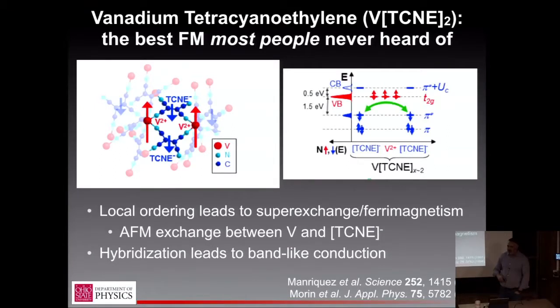I like to think of those as isolated. Well, let's say it's continuous. The issue is, and it's kind of hard to tell from this diagram, that not all of the TCNEs are connected to vanadium on all of their terminal groups. So that means some of them are free to rotate. So while, hypothetically, you can tile space with a crystalline VTCNE, practically speaking, this degree of freedom leads to disorder on some length scale. And that's something we're very interested in tracking down. We're trying to do some collaborations to do small angle neutron scattering to get a feeling for that length scale.